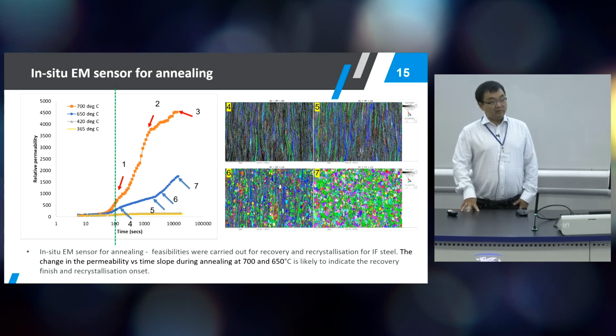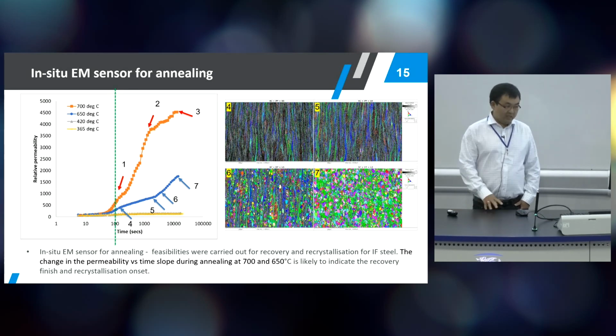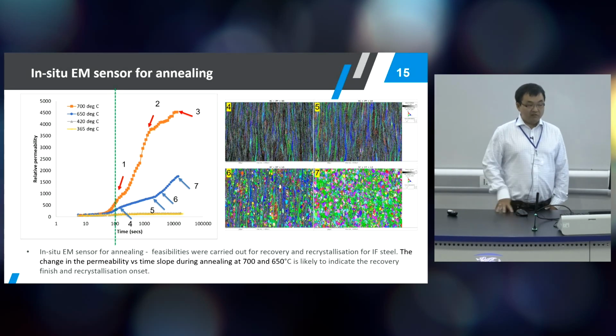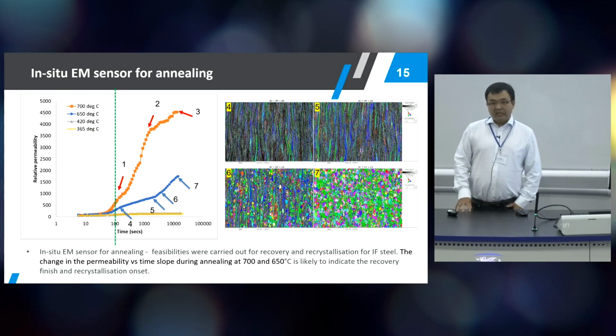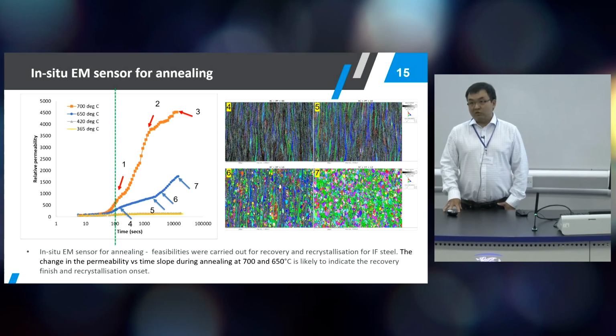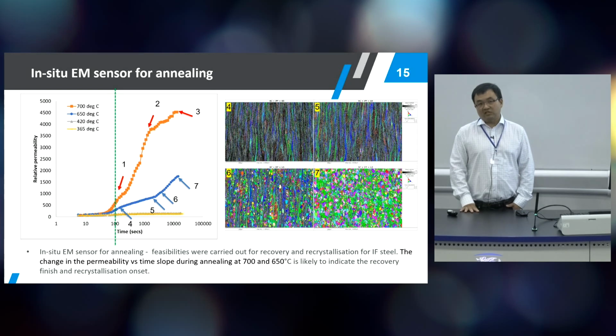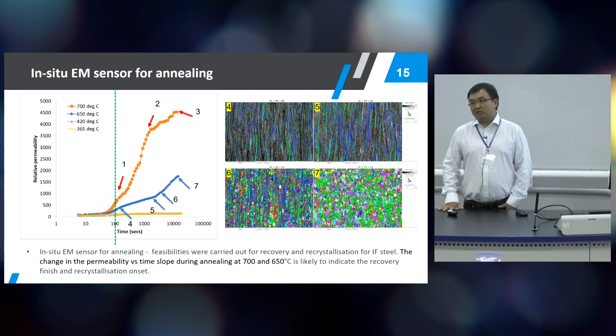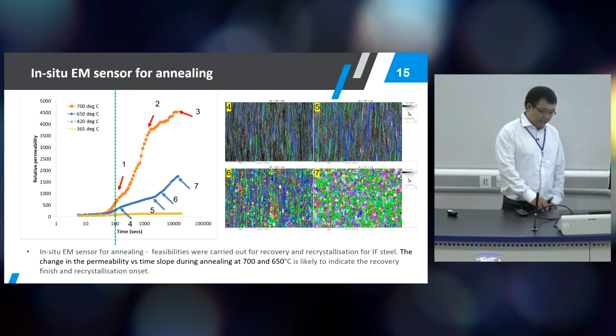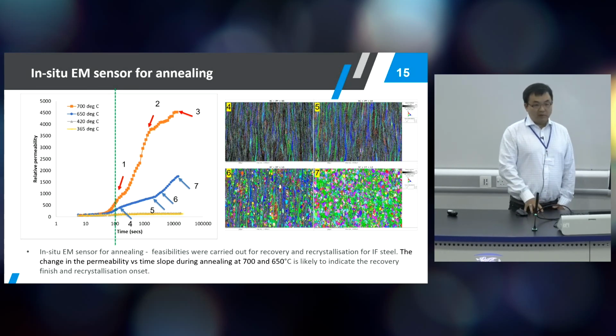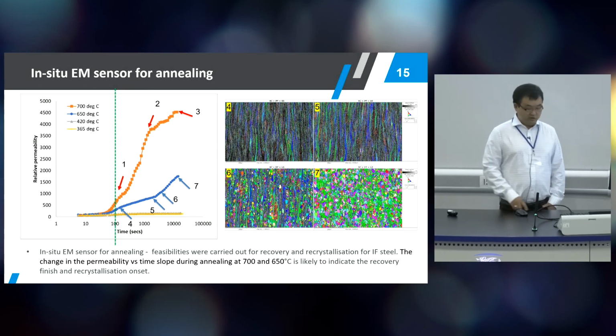Because the sensors seem to pick up the finish of the recovery, the starting of the recrystallization, and the finish of the recrystallization. So that is another milestone to control the microstructure during annealing. It's saving energy. When you achieve the desired microstructure, you don't have to anneal it further. So that's saving energy, and it ensures the microstructure is the one that you want to get.